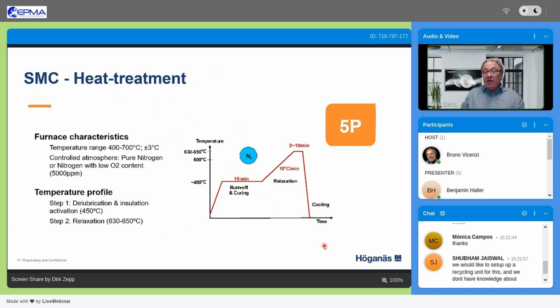The lubrication that has been added to the material up front to make it production-ready needs to be out of the product fully. There should be nothing of the lubrication left in it. And then there is a heat-up phase. During this additional heat-up phase, normally there is an add-on inside the atmosphere of the furnace, either nitrogen or steam, depending on the different SMC materials used for the final product. So each of the different product groups has a certain additional add-on during the heating process.